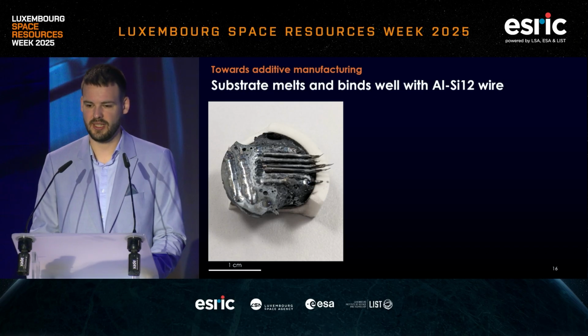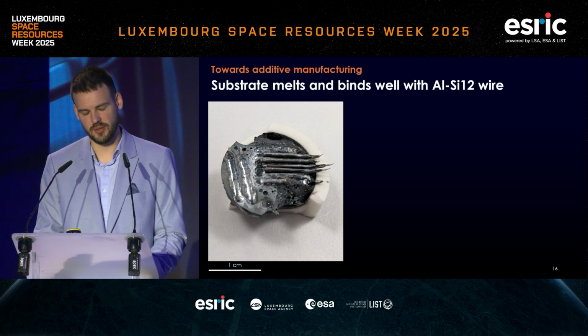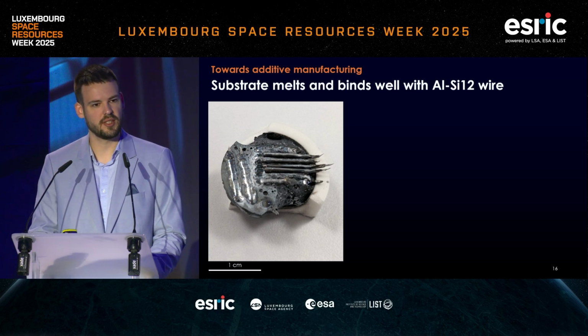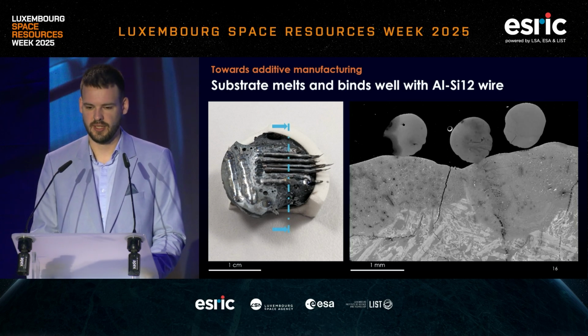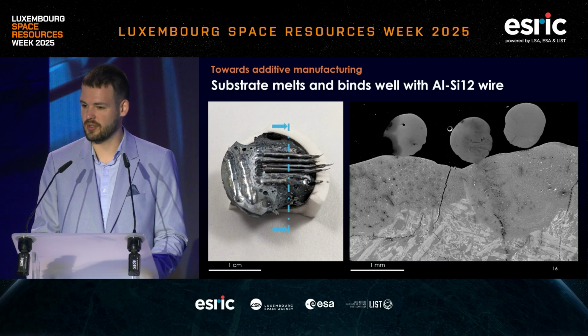So on the left side of the sample, you can see single beads deposited. And then on the right-hand side, we tried stacking 2 layers on top of it. If we look at the section of this under SEM, that's what it looks like. And we can see 3 distinct regions.